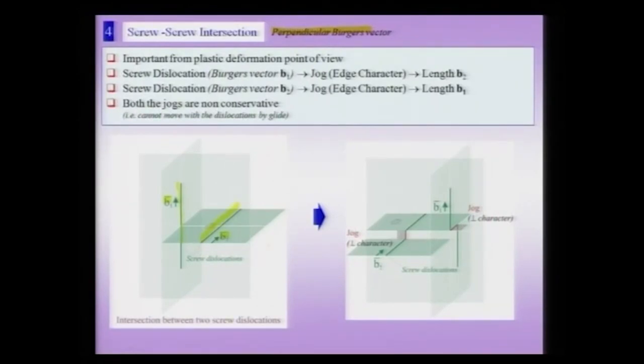So, after the dislocation reaction, you would notice that there is a jog on both the screw dislocations, and both these jogs have edge character. After the dislocation reaction has taken place, there is one screw dislocation with an edge segment in between, which is a jog, and the other screw dislocation also has a small edge segment, which is a jog. So, to summarize this dislocation reaction,